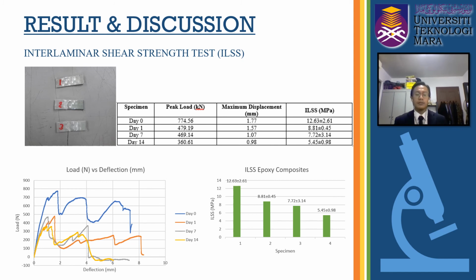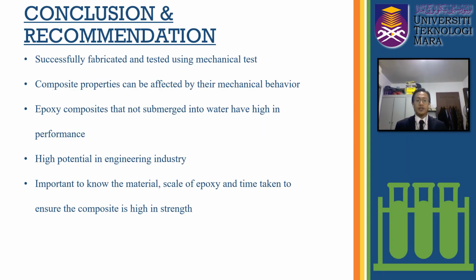High absorption of water is a major disadvantage of epoxy composite, because the presence of water molecules has an effect on the properties of the composites. From the result, it can clearly be seen that specimen 1, which was not submerged in distilled water, has a high ILSS value, which is 12.63 megapascal, while specimen 4, which has the longest submerged time period in distilled water, 14 days, has the lowest ILSS value among the specimens, which is 5.45 megapascal.